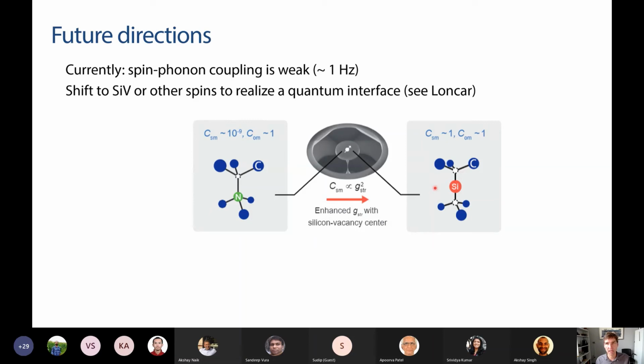But the main message is that one of the reasons the NV center works at room temperature, at least in the ground state, in the sense that it has good coherence, is that it doesn't couple very strongly to phonons. But this, of course, means that its stress coupling isn't very big. So to build a quantum version of this, we will need to go to low temperature, and we probably want to look at a different diamond spin qubit. But that's the bad news.